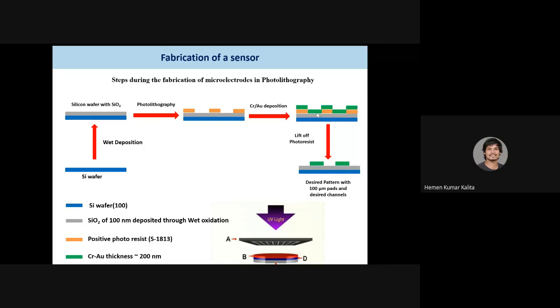So this green layer is basically the chrome gold deposition on the top of the whole substrate. Now there is another process which is known as the lift off process. In the lift off process, what happens? We will remove the remaining photoresist from the substrate. So what will remain? This orange portion will go, and with this orange portion, this green portion will also go off. So what will remain in the substrate? Only the green portion. So these green portions are nothing but chrome gold.